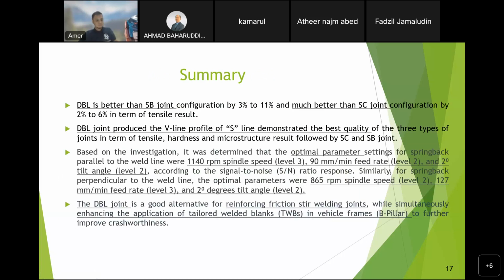So the summary of my two objectives: the first one is that the double butt lap joint is better than the square butt joint configuration by 3 to 11% and much better than the scarf joint configuration by 2 to 6% in terms of tensile results. The double butt joint produces a V-line profile of S-line, demonstrating the best quality of the three types of joint in terms of tensile, hardness, and microstructure results, followed by scarf and square butt joints.